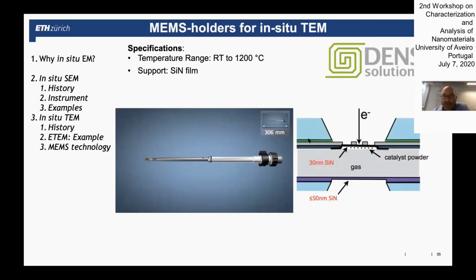The nanoreactor is made of two silicon-based chips with a very thin silicon nitride window. This silicon nitride window is really thin. It's an amorphous film, 30 nanometers thick. And you have two of these windows, and these two windows basically enclose a volume. In this volume, you have your catalyst particles, you have a gas flow, and you can heat. So you have really a microreactor. You just have your small animation.